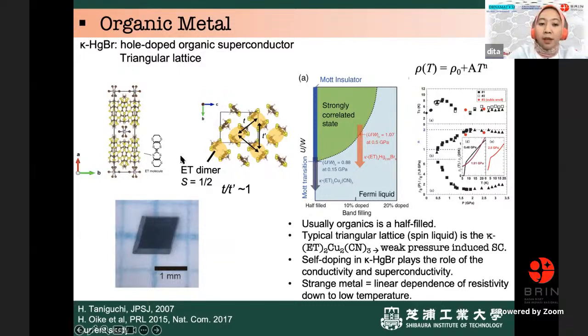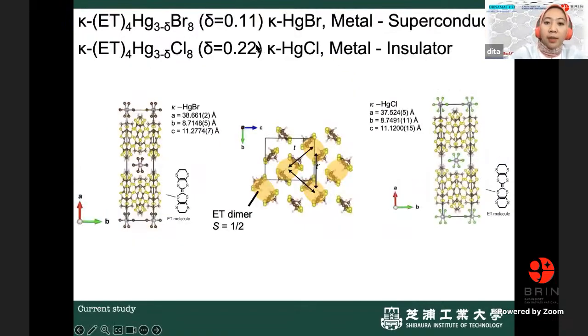However, in the material that I will introduce, there is a self-doping in the material, so-called kappa mercury brome. And then it also has the non-Fermi liquidity. So here is the material. You can see kappa ET4, mercury 3 minus delta bromine 8.